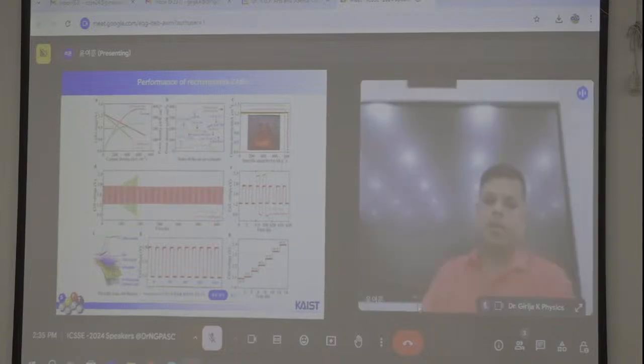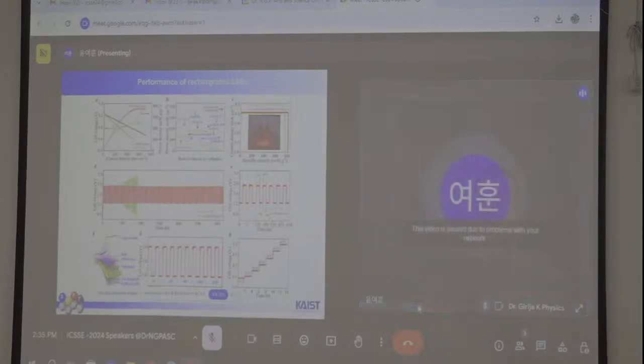Then the performance of our catalyst is around 2 times higher, maybe 1.8 times higher, than the commercial one. Then we can claim that our catalyst gives a higher peak power density compared to even commercial or already reported materials. And we also show the practical applicability by glowing an LED with series connected devices. You can see the KAIST LED is glowing for a long time. Then we can say our material gives practical applicability towards glowing the LED. And the specific capacity and the energy density are also higher than the commercial catalyst.